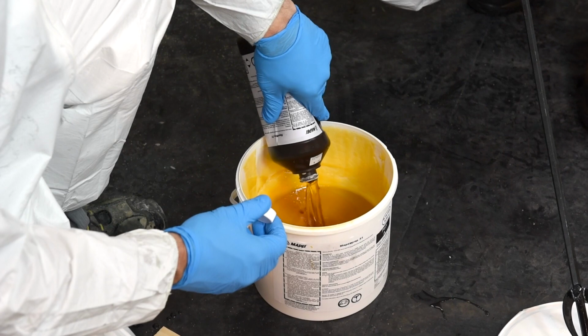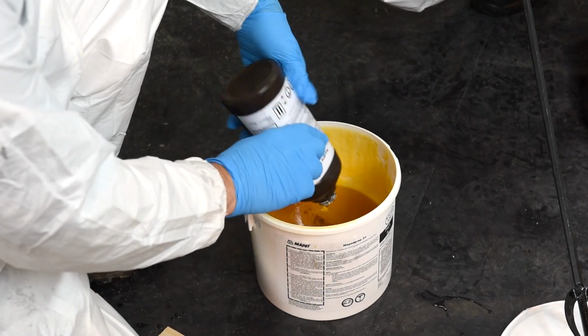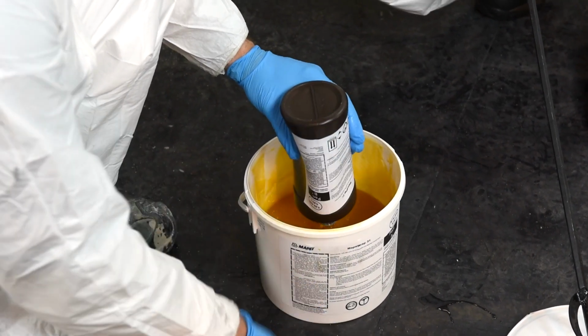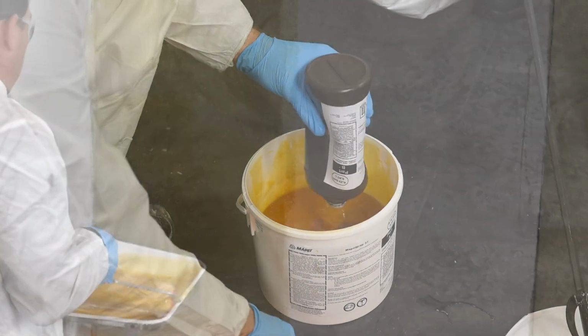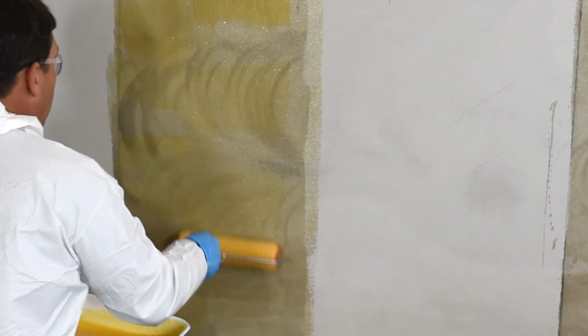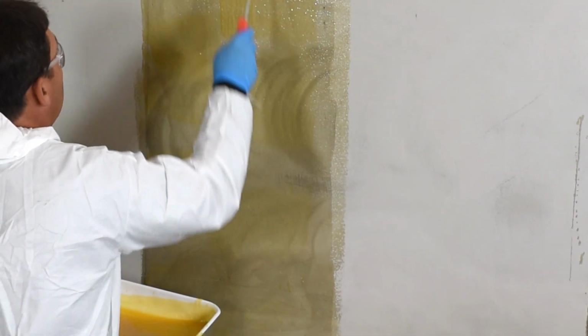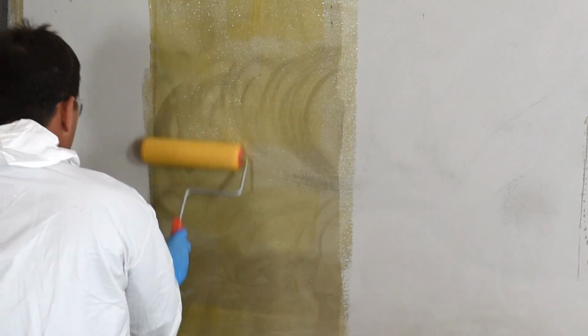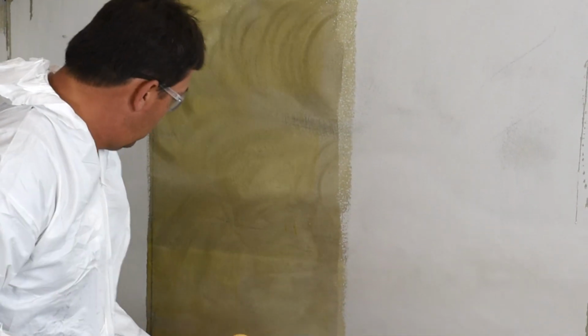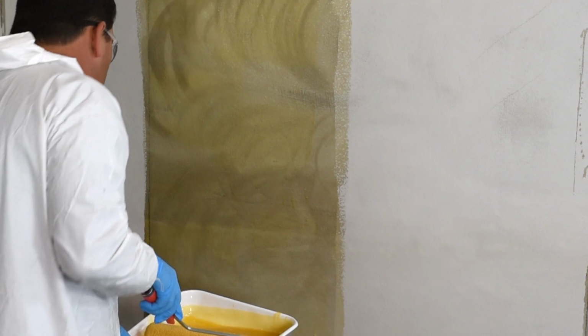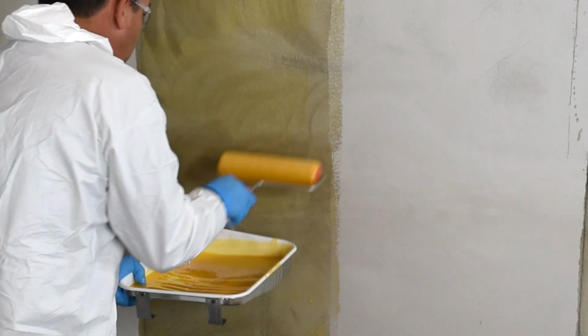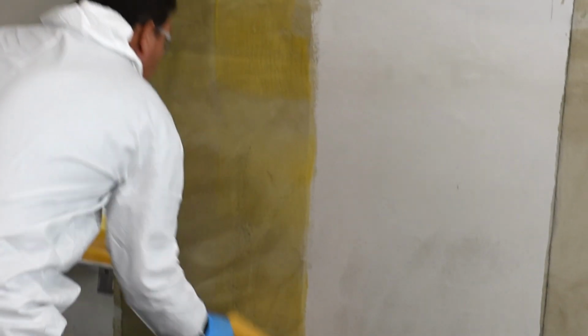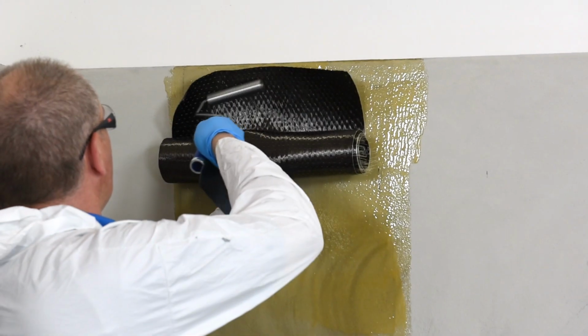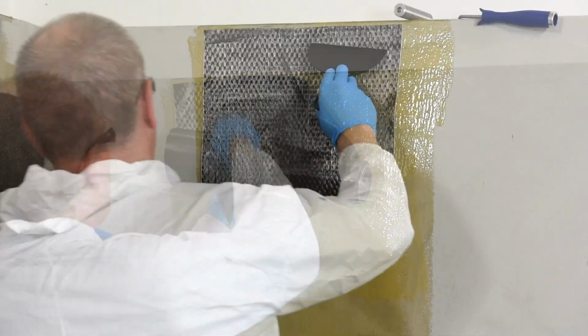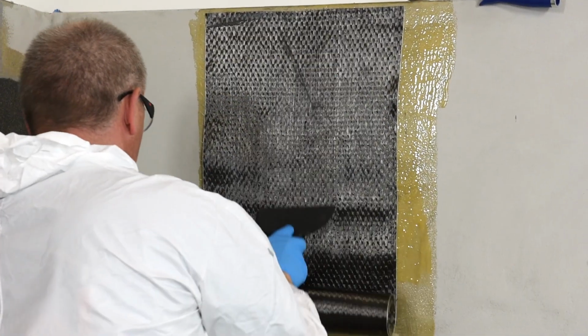MapeWrap 31 saturating resin is mixed and used for a dry layup installation of fabrics. When installing with the dry layup method, the installer uses a brush or a paint roller to apply a uniform first coat of MapeWrap 31 over MapeWrap Primer 1 or optional fresh MapeWrap 11 or MapeWrap 12. Immediately, he will lay out the dry fabric. Next, he will use a plastic spatula to remove any wrinkles or creases.